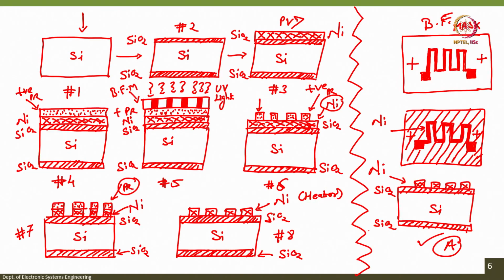Only after hard bake, which is what we do in step number 6, right. After this step number 6, we have to inspect the wafer, and then you have to dip the wafer. If the pattern is correct, if the photoresist is correctly showing the pattern of the mask, right, then you have to dip the wafer in nickel etchant, followed by photoresist stripping, followed by the device which is realized at the end of the process flow. So, this is also called a process flow for fabricating the micro heater.